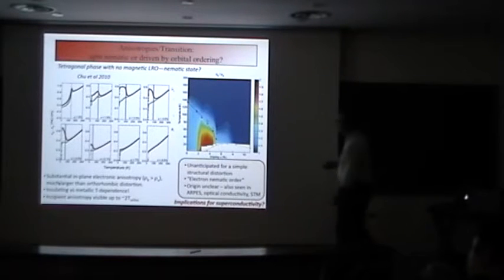But here's an issue that I think is really connected to the relevant physics, which may connect the structural transition with the magnetic transition. This is data from Ian Fisher's group on 122 compounds. Here is the phase diagram of the structural transition followed by the magnetic transition, with superconductivity also present.